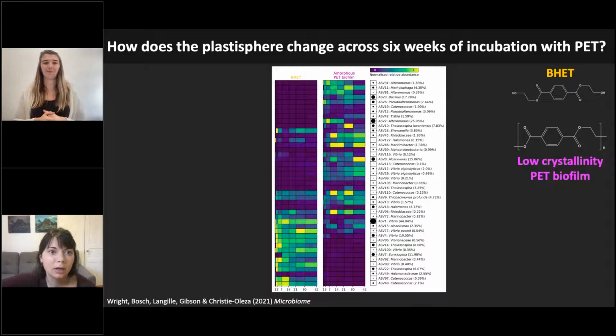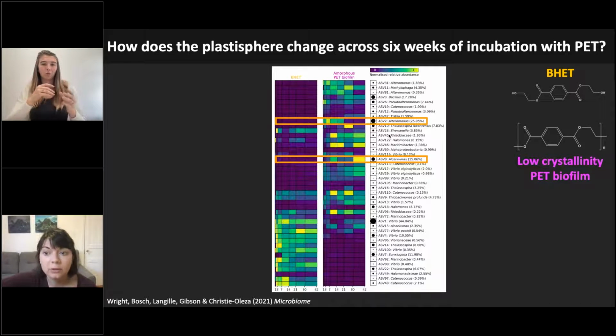So these are groups of bacteria that preferentially like to grow using hydrocarbons such as oil or constituents of oil. And it's the presence of these taxa that usually leads people to suggest that plastic biodegradation might be occurring. And these are actually making up a maximum of 15 or 25% of the communities. So we can see that the community changes over time and that some of these changes might be due to taxa that could degrade plastics. But this is not proven degradation by any stretch.